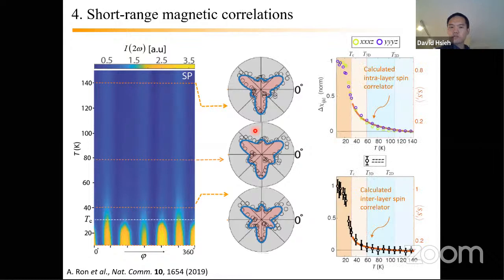And you can then do what I mentioned earlier, which is fit to the tensor for this electric quadrupole process at all temperatures and extract the values of the various tensor elements, let's say chi x, x, x, z, for example, as a function of temperature. And what you find is that this is the data. What we found in this particular compound is that there are two sets of tensors, x, x, x, z and y, y, y, z, that have this temperature dependence above TC, okay? And we've done a classical calculation of the intralayer spin correlator using the experimental parameters, and that's overlaid here in brown.